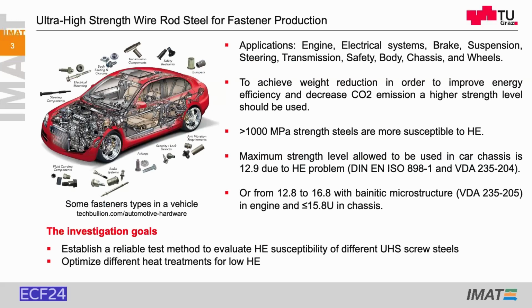Well, ultra high strength steel screws are a part of lightweight construction, where often the problem is that the restriction of the strength of the screws is the hydrogen embrittlement problem, which is normally limited to 12.9, or for bainitic microstructure going up to 16.8. Our goals were to establish a reliable test method to evaluate the hydrogen susceptibility of different ultra high strength screw steels and to optimize the microstructure via different heat treatments to get a high hydrogen embrittlement resistivity.